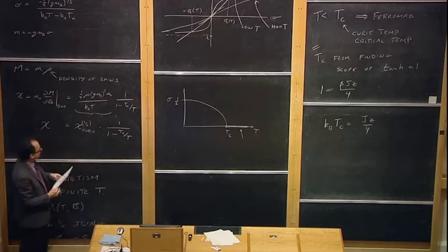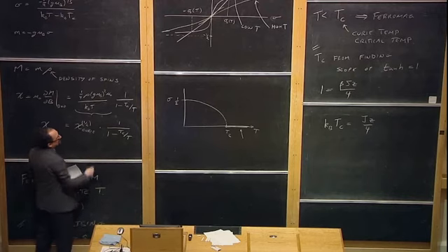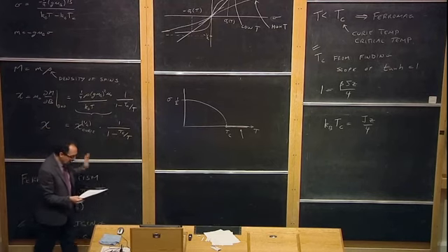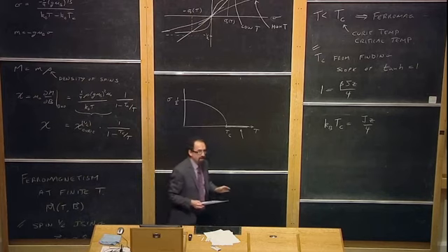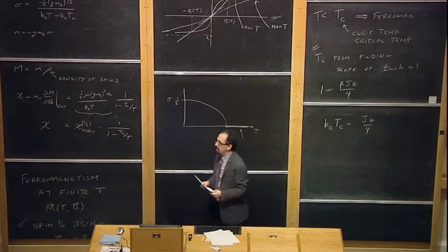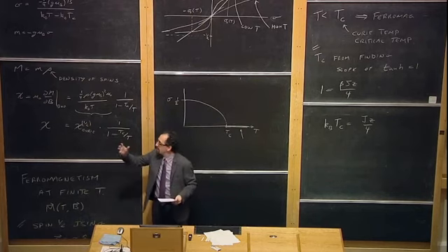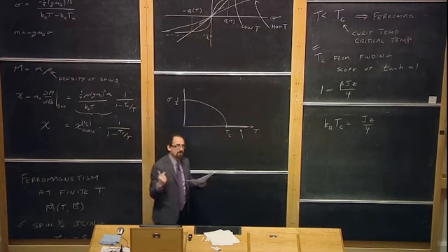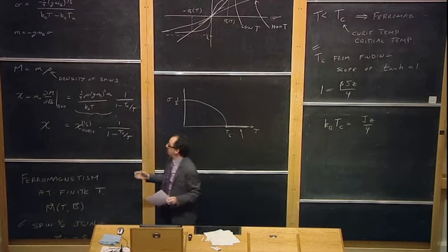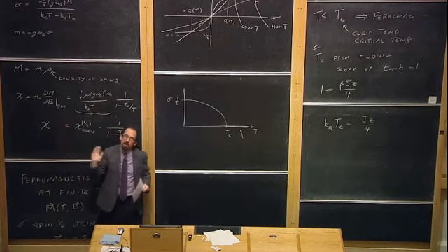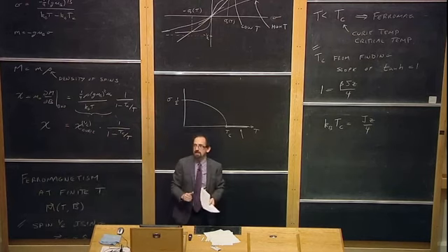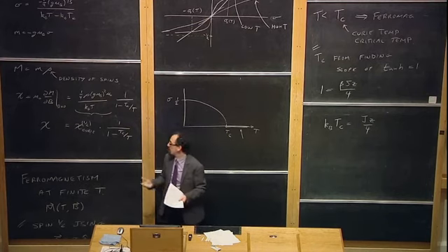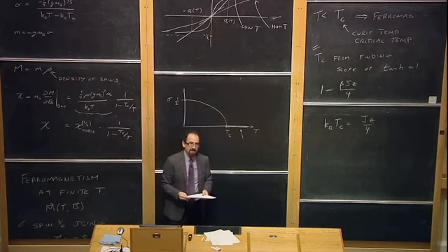Now, you may notice that at the critical temperature, or the Curie temperature, this factor diverges. And that actually is physical. It's real. The reason is that the susceptibility tells you how much magnetization you get when you turn on a little bit of magnetic field, by its definition. But when you go below the critical temperature, you get magnetization even for zero magnetic field. So the susceptibility must have gotten to infinity somewhere along the line. That's what this term is doing there.